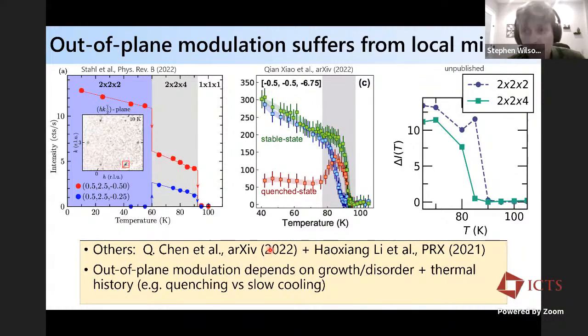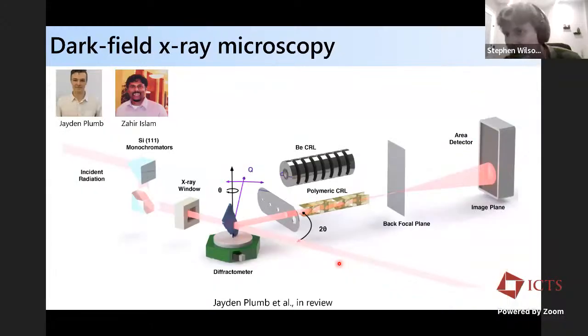And so in some systems, in some of the original reports, for instance, the 2x2x4 superstructure wasn't even observed. And so it implies that this out-of-plane modulation is very sensitive. It's sort of a shallow minimum, I guess, in the energy landscape. And it depends on growth and disorder, as well as the thermal history of the system. And so one of the things that we wanted to do is to try and understand how, in real space, this modulation occurs.